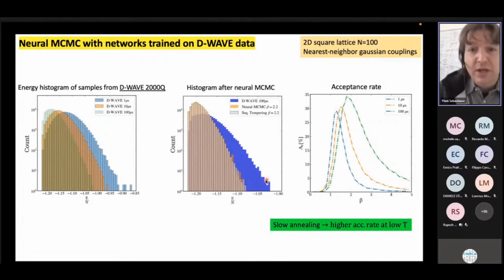So here you see in blue the original distribution of the data from the quantum annealer. Okay. With the gray color, what we obtain with our computationally expensive sequential tempering procedure at low temperature. Here beta is equal to 2.2, so you're very close to the ground state energy. And you see that the data from the neural Monte Carlo simulations are unbiased. Okay, so this shows you that the neural network is ergodic enough, let me put it this way, to propose updates that explore the full configuration space.